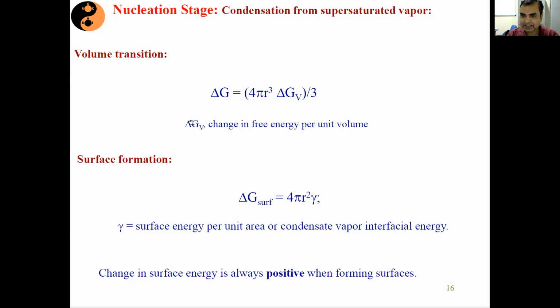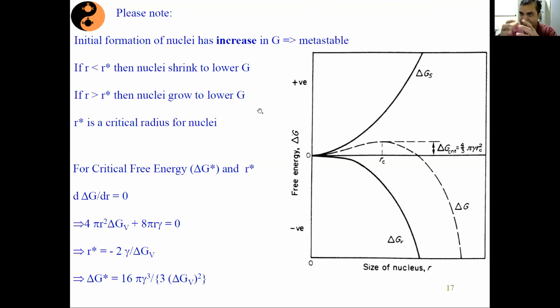And it so happens that delta GV is negative because it tries to bind the things, whereas surface tension is a positive energy. Okay. So negative energy means bonding, positive energy means breaking, as simple as that, right? So to have a stable nucleation, we need to have a net energy negative. Now, when we have a competition of these two energies, the surface energy and the volume energy, you can see that the surface energy is positive, volume energy is negative. For a smaller radius, delta GS will be higher than delta GV. Of course, you can see that delta GS has only R square dependence, delta GV has R cube dependence. So how come delta GS is larger than delta GV?